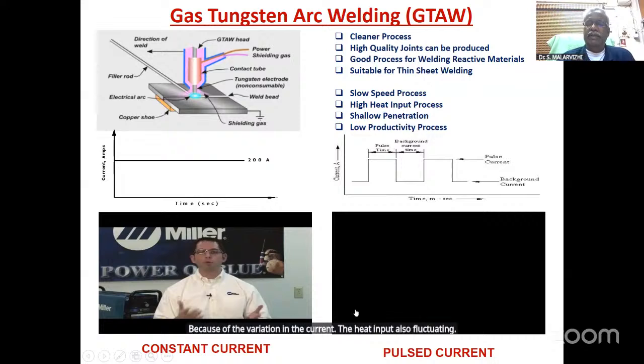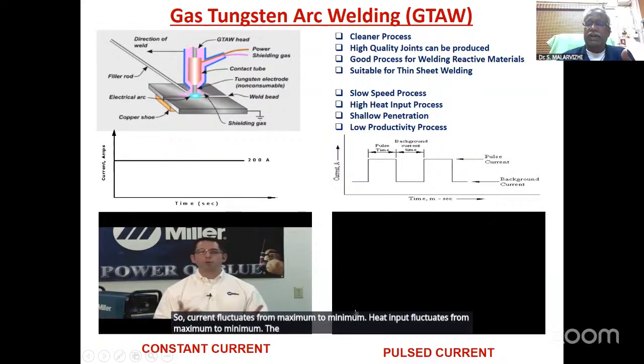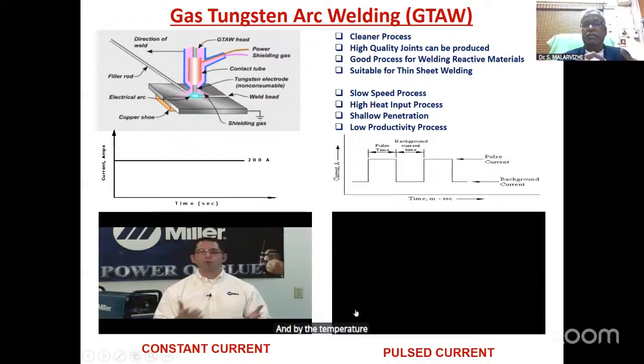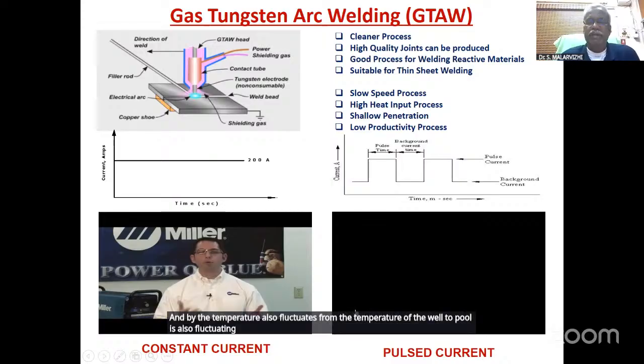And not only that, surrounding the arc there is always an electromagnetic force. That force is also fluctuating from maximum to minimum. So current fluctuates from maximum to minimum, heat input fluctuates from maximum to minimum, the arc force also fluctuates from maximum to minimum, and the temperature of the weld pool is also fluctuating from maximum to minimum.